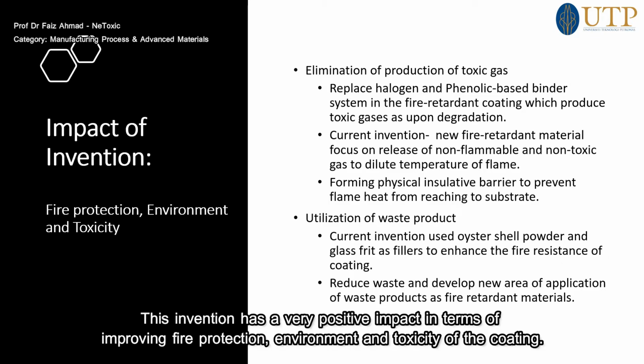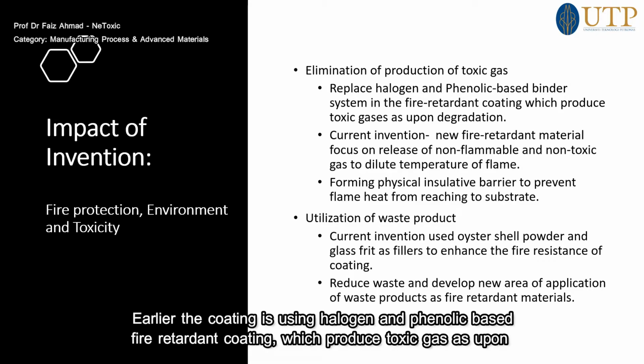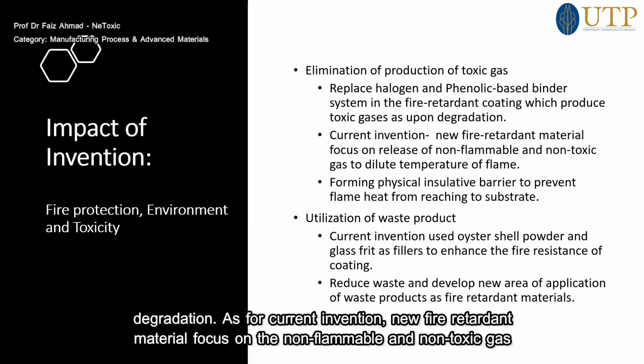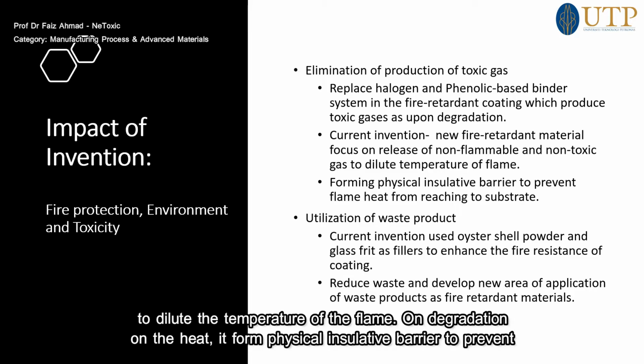This invention has a very positive impact in terms of improving the fire protection, environment, and toxicity of the coating. Earlier, the coatings were using halogen and phenolic base binder systems in the fire retardant coating, which produced toxic gases upon degradation. In the current invention, the new fire retardant material focuses on the release of non-flammable and non-toxic gas to dilute the temperature of the flame, and then on degradation by the heat, it forms a physically insulative barrier